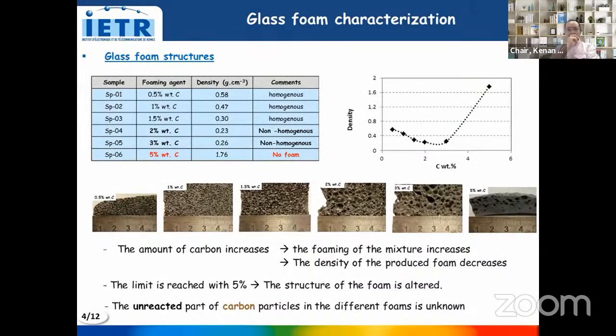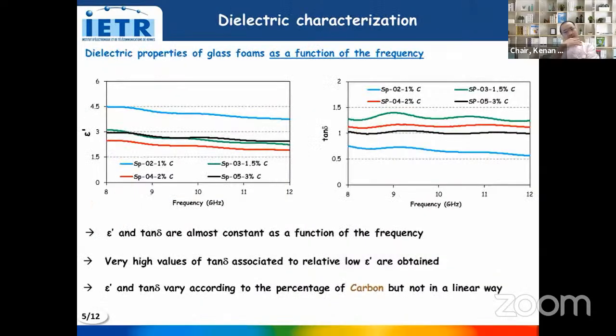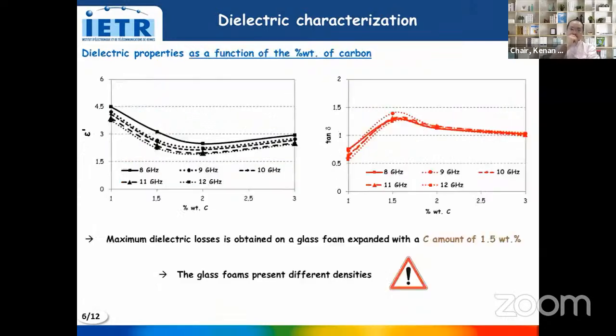This curve and these photos show that when the amount of carbon increases, the foaming of the mixture increases and the density of the foam decreases. The limit is reached with 5% of carbon, for which the structure of the foam is altered. For the dielectric properties, we can note that very high values of dielectric losses are obtained for the samples and are associated with relatively low permittivity. However, the dielectric properties vary according to the percentage of carbon, but not in a linear way.